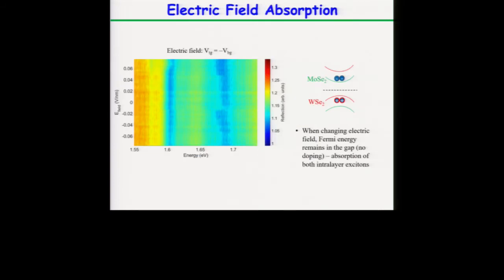If we look at absorption on the heterostructure, we can still see the MoSe2 and tungsten diselenide absorption, so we haven't doped the sample. The sample is still intrinsic, so the Fermi level is in the center. What we are doing with this electric field configuration is just stretching this dipole moment.